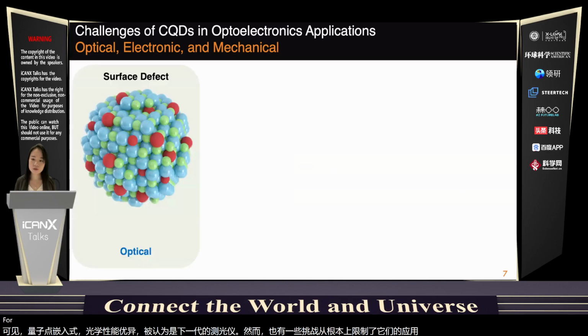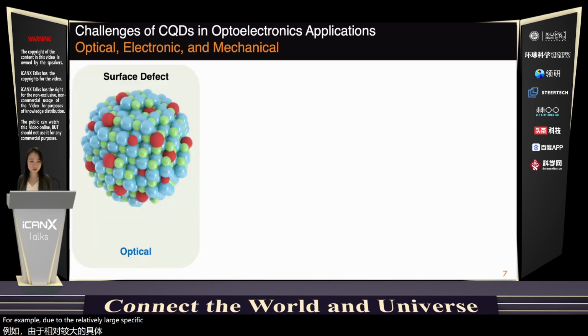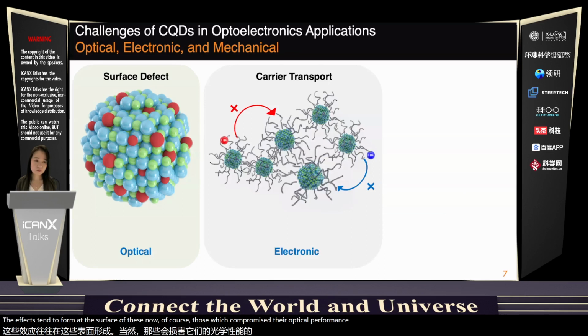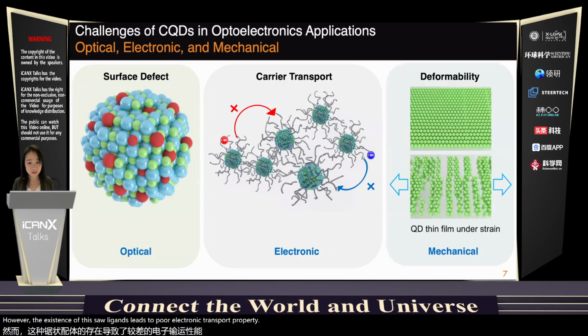For example, due to the relatively large specific surface area, defects tend to form at the surface of these nanocrystals, which compromise their optical performance. Ligands and shells are often used to passivate or remove these electronic defects. However, the existence of these ligands leads to poor electronic transport property. Lastly, quantum dot thin films are mechanically brittle. They tend to form cracks when being bent or stretched. That limits their application in wearable and biointegrated electronics.